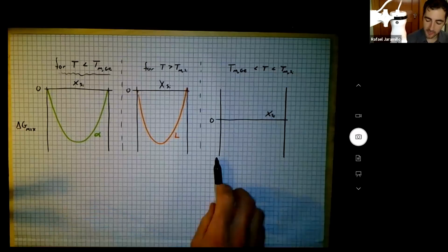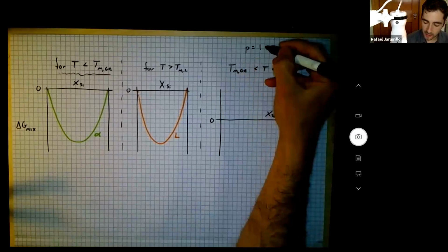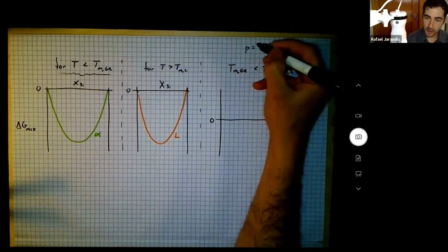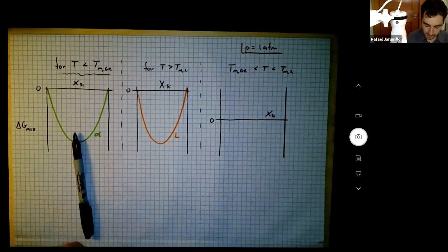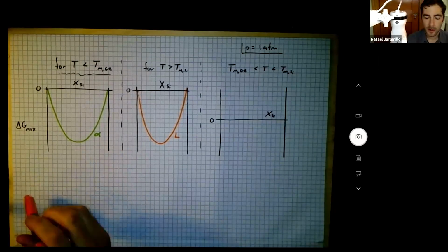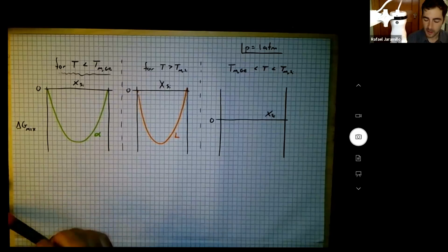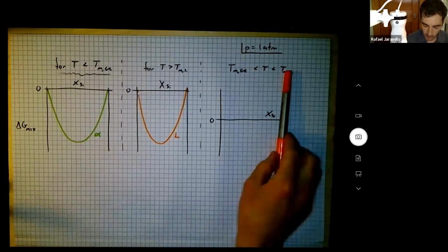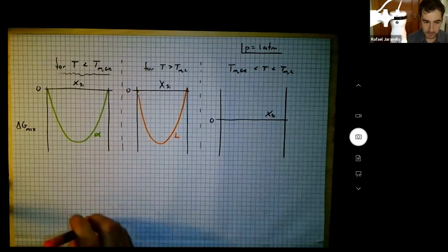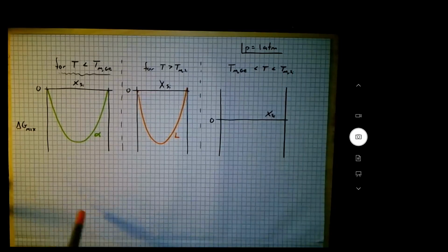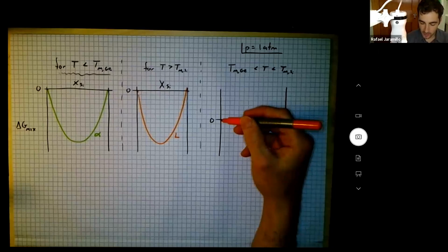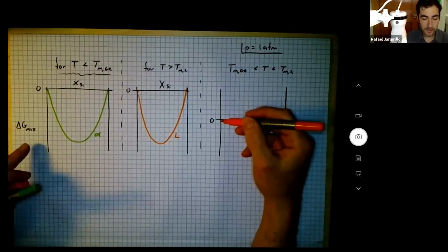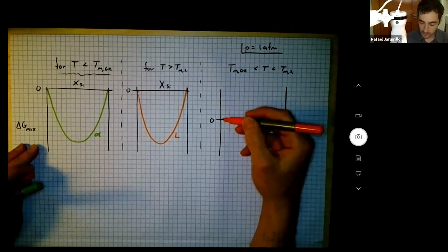It's unstated, but the pressure is 1 atmosphere unless stated otherwise. So what is the reference state? What's the phase of germanium in this temperature range? Liquid. So my liquid phase solution model is going to start from 0, because the free energy of turning pure germanium into a liquid is 0. It already is a liquid.